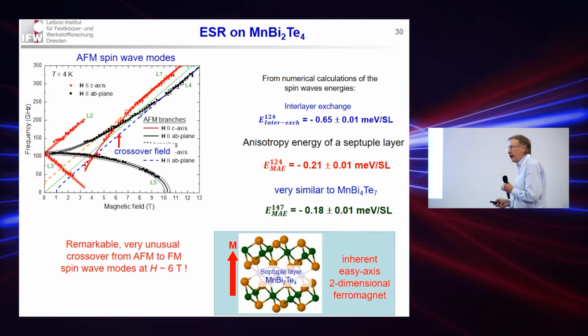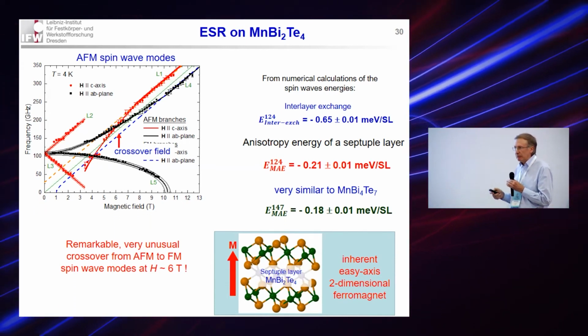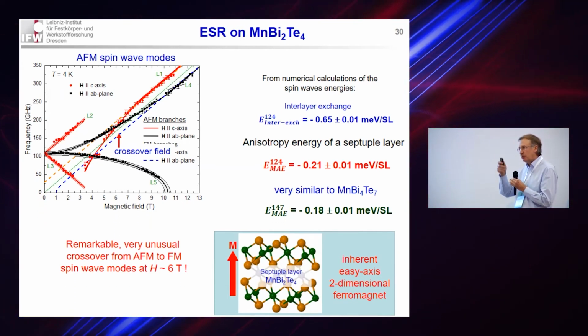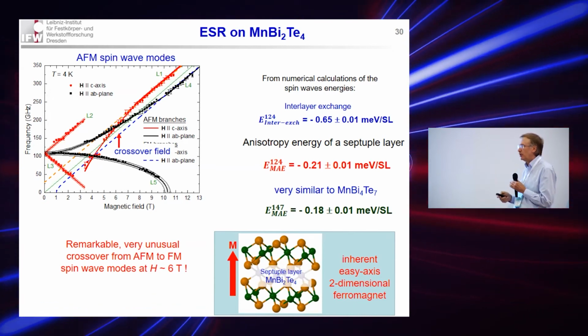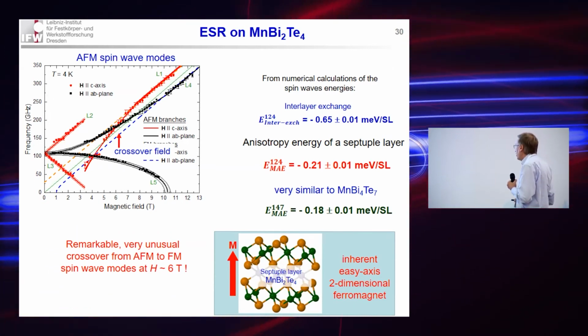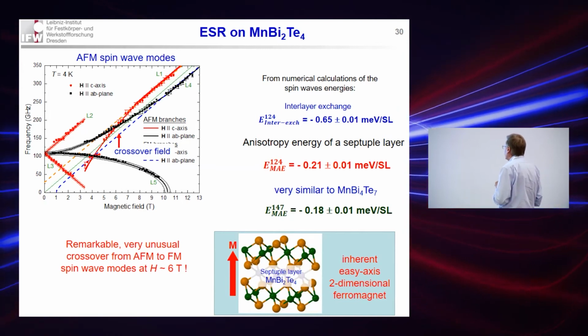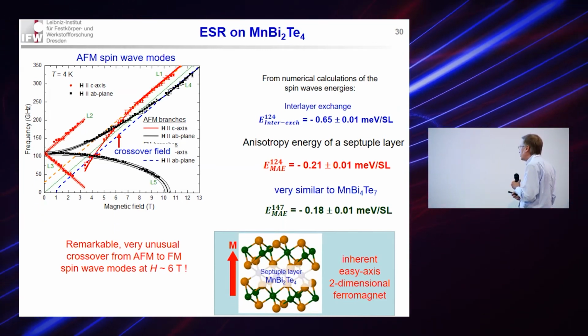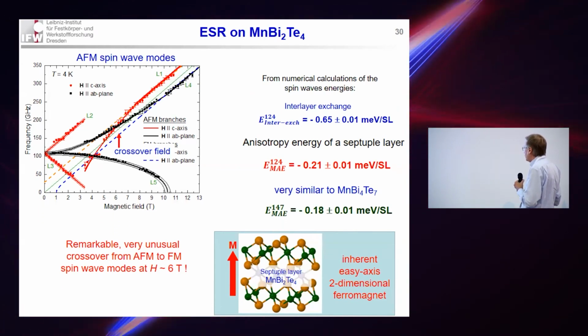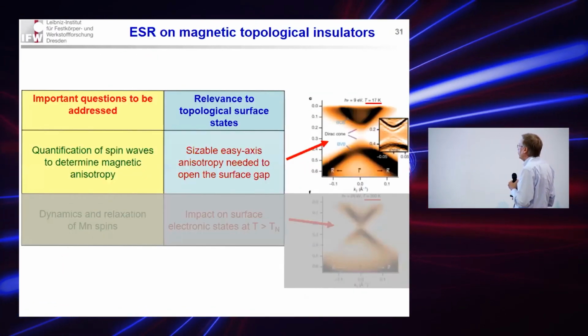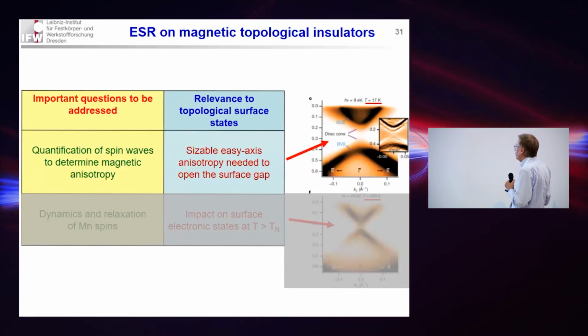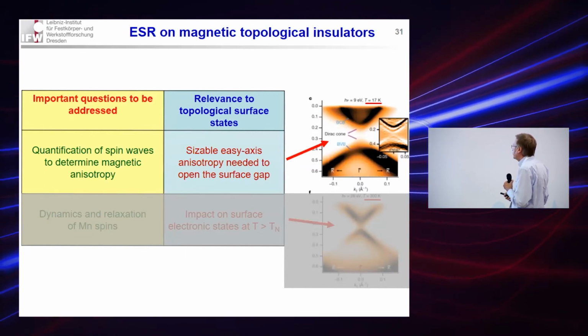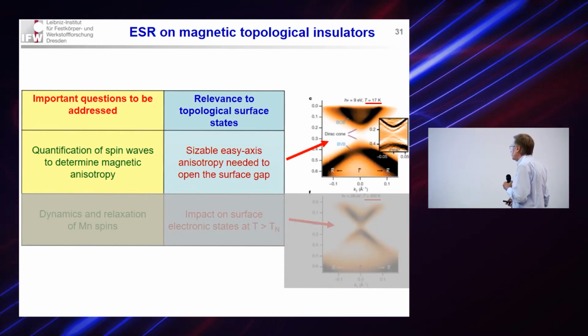So the details of the structure are not so important. Either it's separated by 1 or 2 or 3 non-magnetic layers, so the magnetism is confined to these individual layers, and it's stable, and it is out of plane. So that is quite important for the realization of the surface gap in the electronic states, which is observed experimentally.